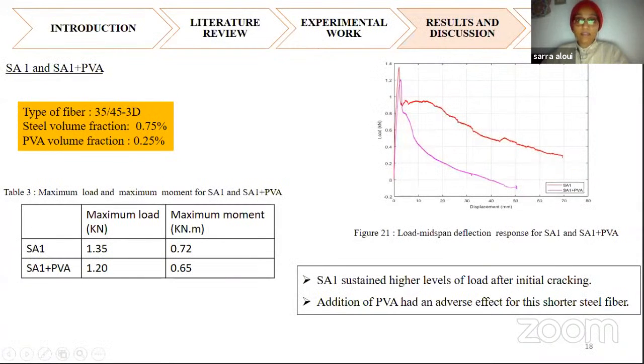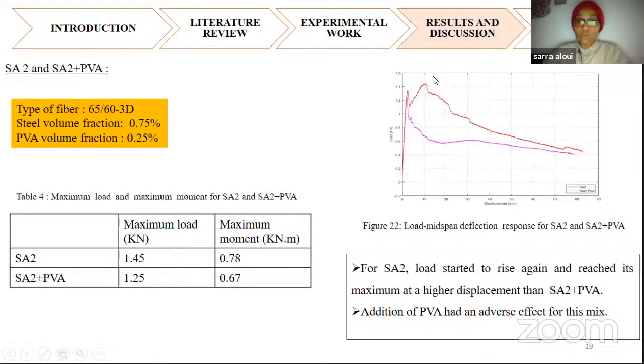Now we are passing to the results and discussion part. Here we can see that for the first specimen, SA1, the specimen with the usage of PVA has a lower maximum load compared with the specimen with the steel fibers. Here we can say that the addition of PVA has an adverse effect for the short steel fibers. For the second one, SA2, we can also see that the load dropped for the specimen with the usage of steel fibers and then rises again. Here we can see the difference between the maximum loads for both specimens. We can say that the addition of PVA has an adverse effect for this mix.